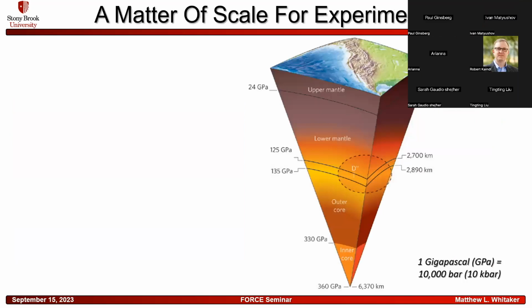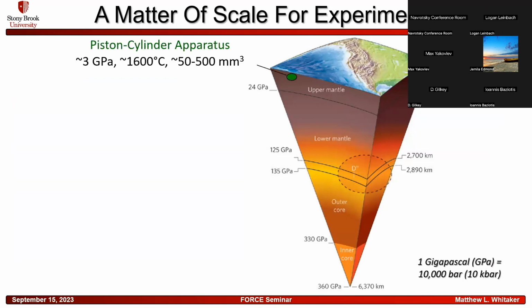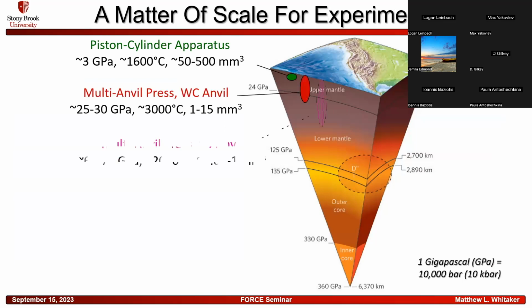And there is a matter of scale of these experiments as well. Just for reference, 1 gigapascal here is 10,000 bars, which is the unit that I was using previously. So when we want to replicate some of these conditions, we have the piston cylinder apparatus, which is capable of achieving pressures of up to about 3 GPa and about 1,600 degrees centigrade. And the sample size is relatively large. It's 50 to 500 cubic millimeters. The multi-anvil press, depending on if you use tungsten carbide anvils, which is the standard, or sintered diamonds, which are much more expensive, generally runs with a maximum of about 25 to 30 GPa and 3,000 degrees with a sample size of 1 to 15 cubic millimeters.